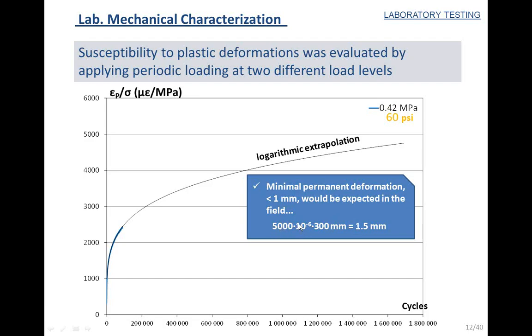If you multiply the plastic strain by 300 millimeters, which is the thickness of the layer, you would obtain only 1.5 millimeters. Of course, this is quite unrealistic, because this level, 60 psi, would only take place at the top of the layer. At the bottom of the layer, the vertical stress would be so much lower. So the main conclusion is that we should not be expecting permanent deformation from this material.